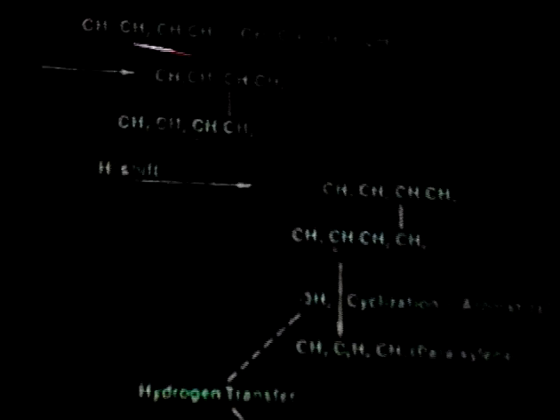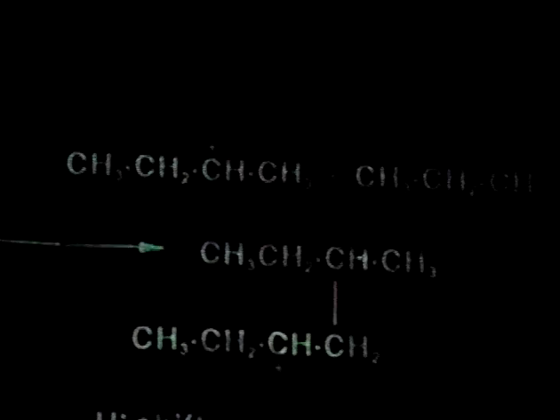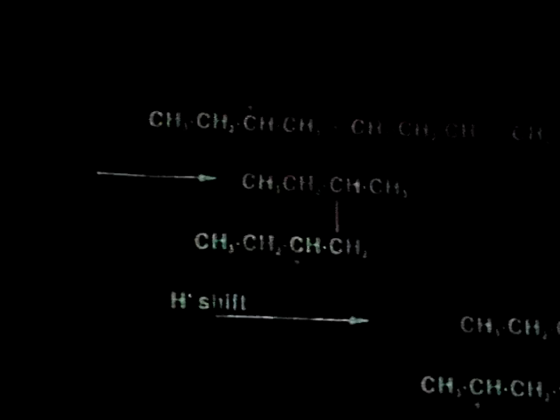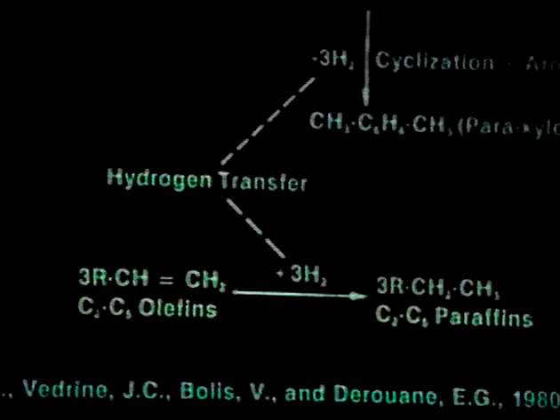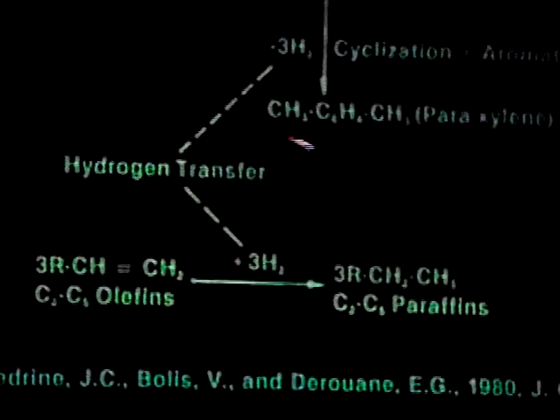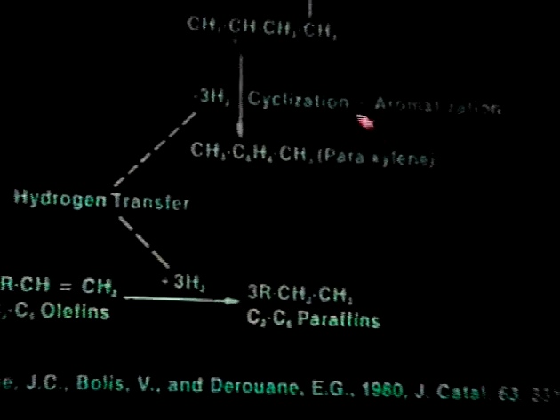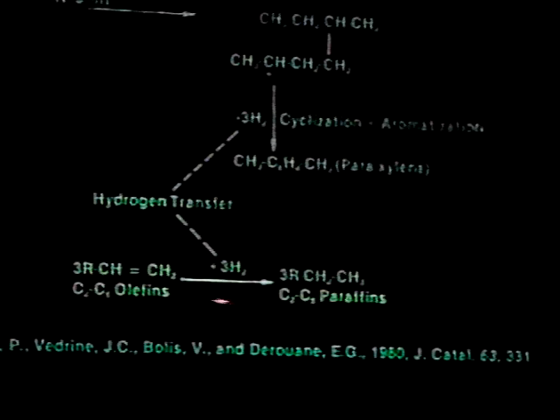A mechanism that one can conceive for this correlation is the familiar mechanism given by Derouane and collaborators. If you consider butene to be one of the primary Fischer-Tropsch products, then through acid-catalyzed reaction, butene is polymerized to a branched form of octene, which then undergoes a hydride shift, giving a species such as this. These are all carbenium-ion interactions happening on ZSM 5, which also catalyzes the further reactions through cyclization and aromatization to give you, say, para-xylene. However, in this process, you will see that it has to lose 6 hydrogen atoms, and the hydrogen is then picked up by other olefins, especially the light alkenes, which are also in the product stream.